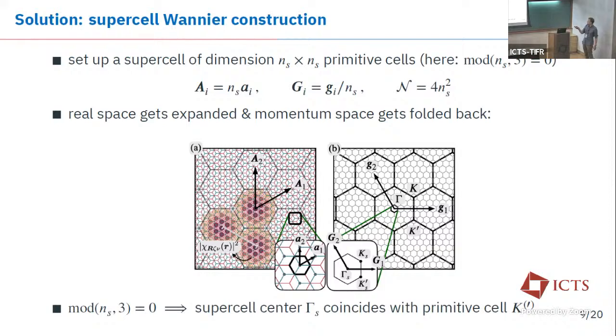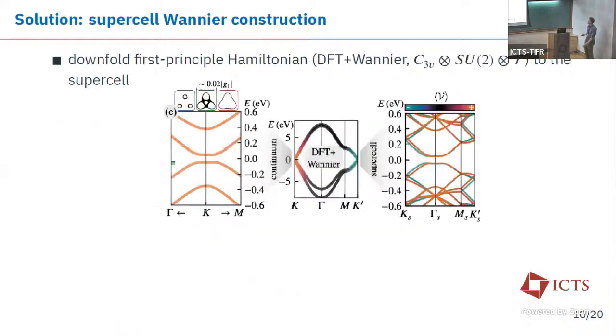Now, a side note is that we take supercells that are divisible by 3 in terms of the original unit cell, and that is because then the supercell center, the gamma supercell point, coincides with the primitive cell valleys, and therefore all phase factors are trivially contained because everything we need to do is look at the gamma point of the supercell. So this makes things particularly simple, but it's not a necessity. This is just a technical simplification. What we do when we have our supercell is we take our first principles Hamiltonian. So this is a Wannierized DFT Hamiltonian with a certain set of symmetries.